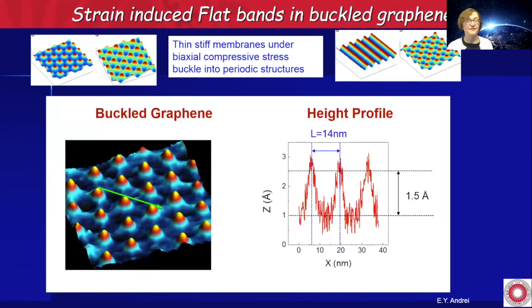So we did that with graphene. This happened accidentally by differential thermal contraction, and we were able to create a buckled graphene structure. This was graphene that was deposited on niobium diselenide. And again, this was another instance of serendipity. The results that we saw were completely unexpected. We created this buckled structure. You see it's a triangular structure. And if you plot the height along this direction, you see that you have a height modulation of about 1.5 angstroms.